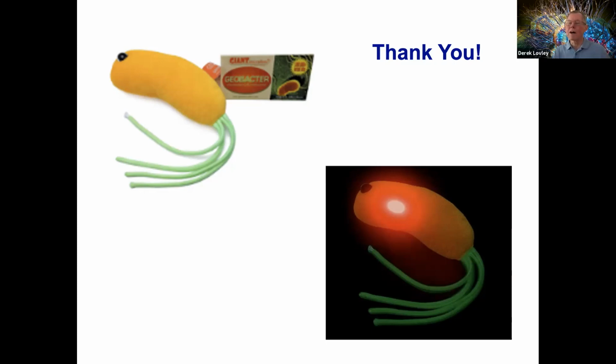Yep. So yeah, that was done early on by Nikhil Malvankar. But I want to make it clear, it hasn't been done on an individual filament, but it has been done on thin films, or at least his work was on thin films. So what he saw was as you decrease the temperature, then the conductivity would, at a certain point, start to increase.